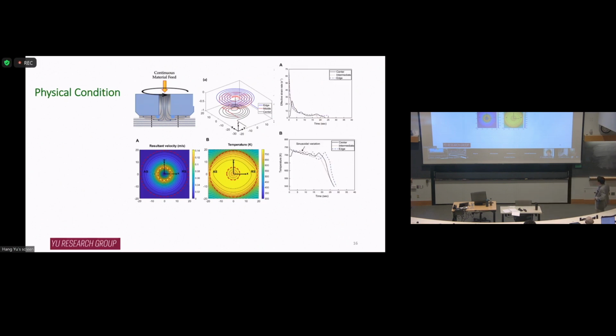So this is typically what we get. The top one is the strain rate history. Initially, once the material comes out of the channel, there's a high strain rate. Usually it's a short period of time, about a second or so. And then the strain rate will decrease. For temperature, as long as the material is below the printhead, it's experiencing pretty high temperature. So there's an extended period of time that the material is under elevated temperatures. And this is consistent with what we find from the in-situ measurement as well.